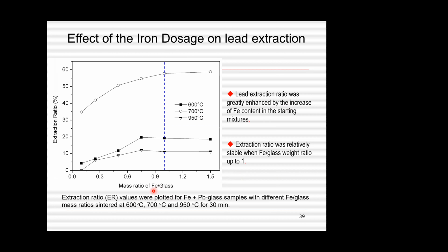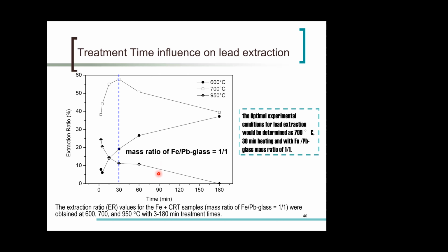So we find out you need to add zero valent iron, but you don't want to add a huge lot of them because it's wasting money, right? So we find out probably you should add it close to 1, but don't need to be over 1, or even you add about 0.9, depending on the temperature you're going to operate. You can just add the iron to be enough instead of too much. Too much iron is not necessarily boosting up your performance, just basically wasting more iron.